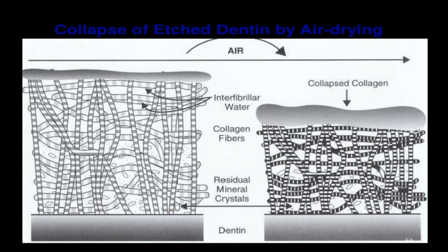Two approaches can be followed, depending on the type of adhesive system used: A dry bonding technique, which involves air drying of enamel and dentin and applying a water-based primer capable of re-expanding the collapsed collagen network. B. Wet bonding technique, which leaves dentin a little moist to prevent collapse of the collagen and uses a solvent-containing primer to chase water from both dentin and enamel. Wet bonding technique is more consistent and reliable. 63. Collapse of etched dentin.